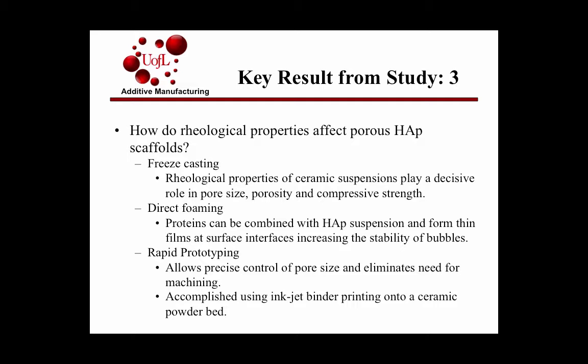Direct foaming was the next process they examined, where proteins are combined in the HAP suspension, and they attach to the surface of the present particles, and they form bubbles between them, getting that porosity. And then finally, the rapid prototyping component of this paper was maybe half a page. They addressed that it allows precise control of the pore size and eliminates the need for machining, and they accomplished all these parts using an inkjet binder printing method on a ceramic powder bed. Like I said, they didn't really address it, but they did mention it as being one of the best options going forward because it gives you the most precise control over the parts you're making.